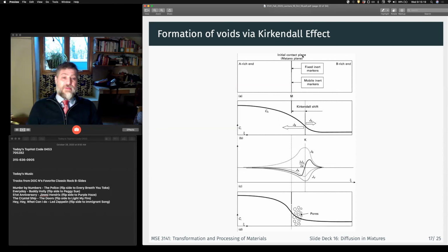Okay. Anyway, for this interdiffusion and the Kirkendall effect, I rushed this a little bit at the end of Monday, and I'm afraid I may have said something confusing. So I want to take a couple seconds and go through this a little bit more carefully. So here we have a diffusion couple between A and B, right? We stick them together with some inert markers like the molybdenum wire in the experiment from Kirkendall, right? And where they are originally in intimate contact, this is known as the Matano plane or